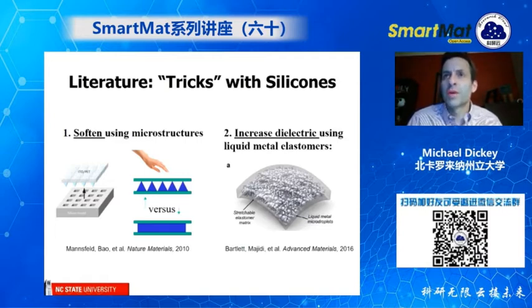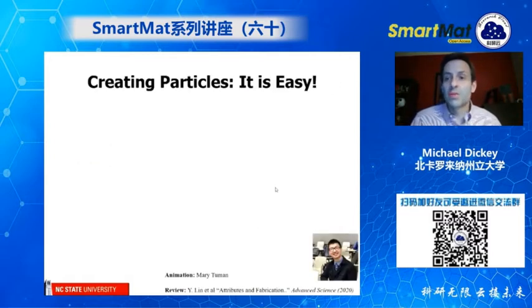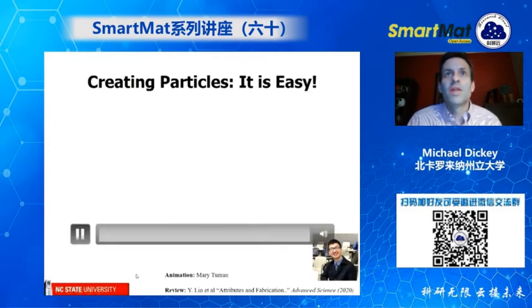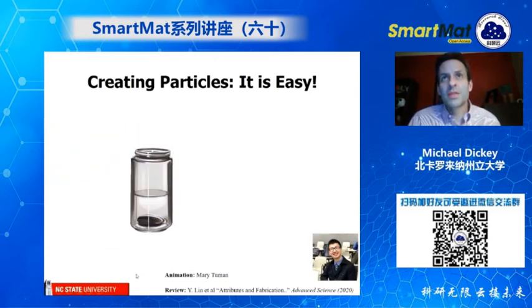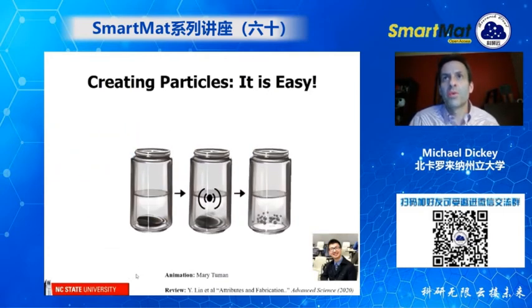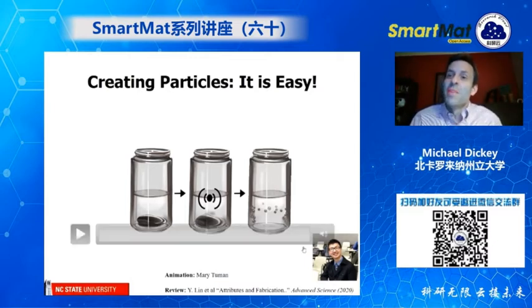Another really nice work is from Mike Bartlett and Carmel Majidi, where they mixed liquid metals in with elastomer, and that increases the dielectric constant, but it doesn't make the material stiff, so it keeps it very, very soft. So inspired by this, we set out to make some particles, and this is actually very easy. You can just take liquid metal and essentially stir it or sonicate it, and it will break up into little droplets. And we have a review on these techniques. And so Jia, the student that I mentioned, this was another review from a really great Chinese student, Yiliang.